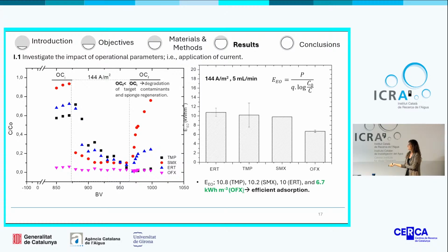On the other hand, the energy per order was calculated, and according to the result, in the case of the highest current applied and a medium flow rate, we could observe ofloxacin had the lowest value, which again highlights the importance of an efficient adsorption and interaction with the electrode.